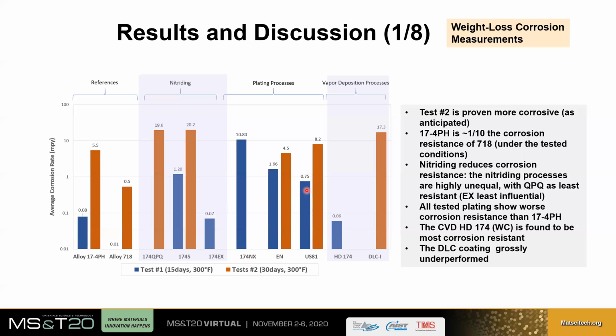Obviously it corrodes a bit less in the first test than in the second test, as seen earlier. It does corrode quite a bit. So where there is a bit more light out of the tunnel is actually with this particular coating, HD. HD essentially is a nanostructured tungsten carbide. And this is the only coating out of this investigation that turns out to outperform